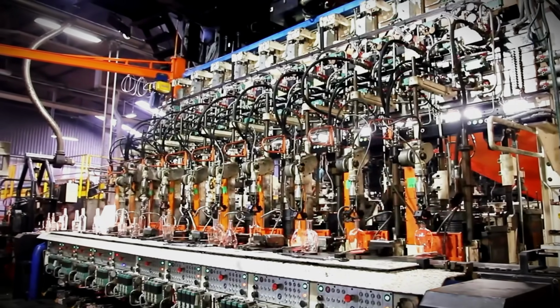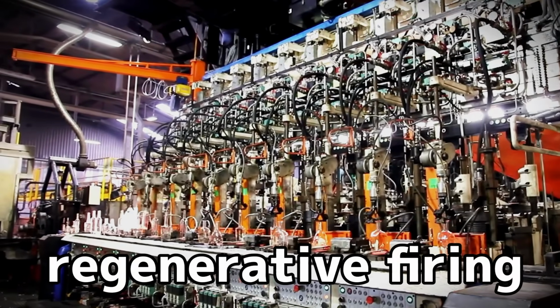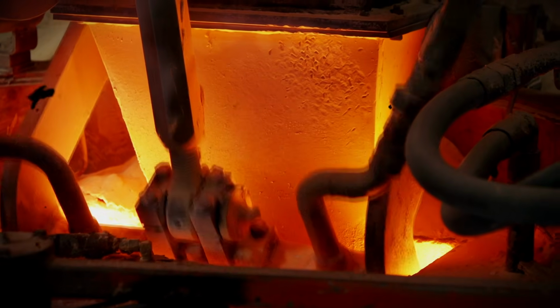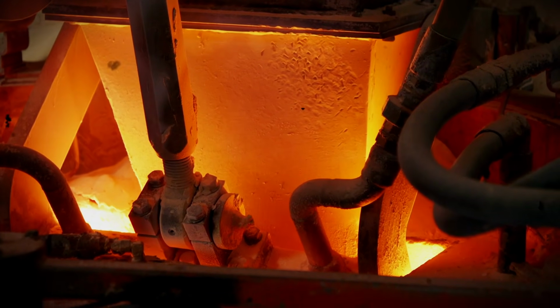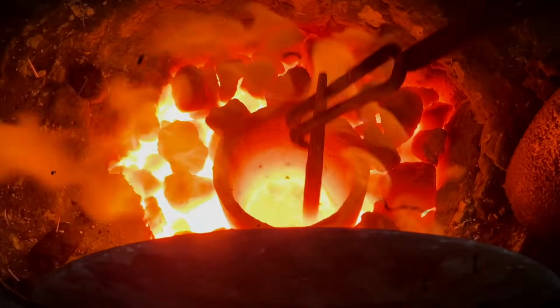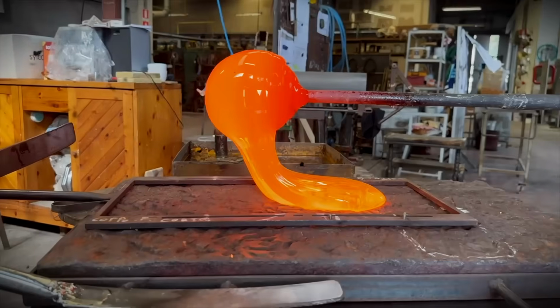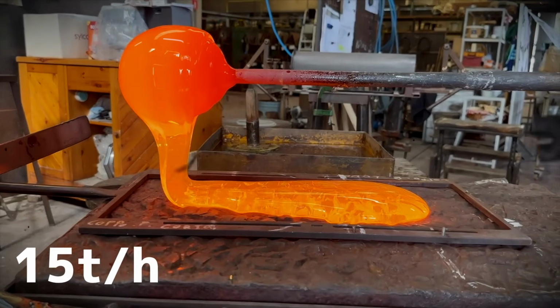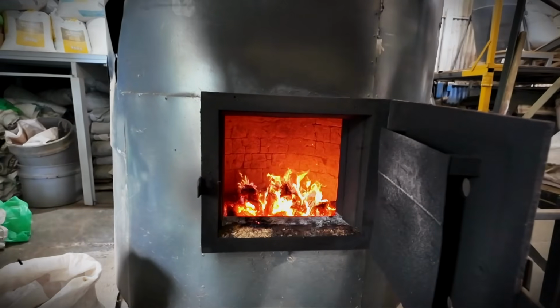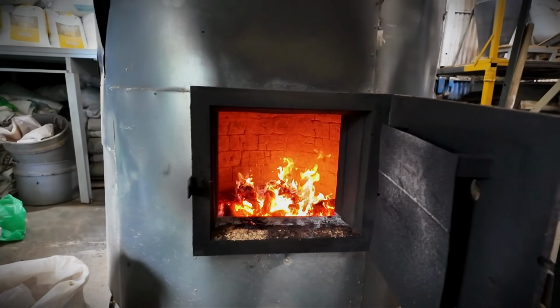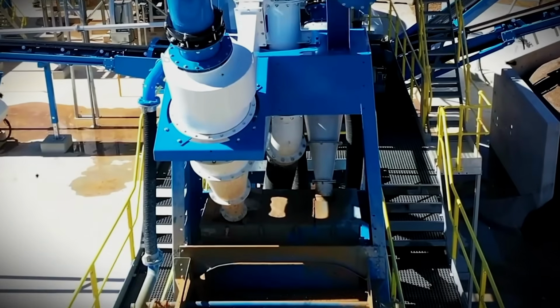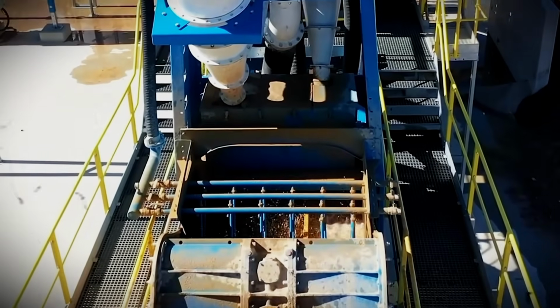The flames switch sides every 20 minutes in what's called regenerative firing, where exhaust heat preheats incoming air, boosting efficiency up to 50%. Raw batch pours steadily in at 15 tons per hour. Over the next 16 to 24 hours, it slowly dissolves into molten glass. Workers monitor everything from a control room with over 50 thermocouples throughout the bath. Even a 10-degree deviation can ruin the entire batch.